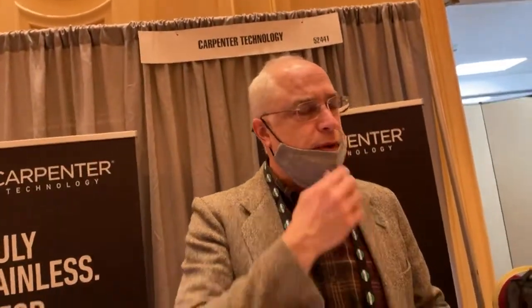Exactly right. So anyhow, after we carburize it and we get up to 62 Rockwell C, we'll throw it in a salt fog corrosion test chamber. Picture something about as big as this tape. Do you know what that is? Yeah. Okay, super. So it's 95 degrees Fahrenheit, 100% humidity with a 5% sodium chloride solution. It's nasty. Most steels that are hard will rust within an hour.